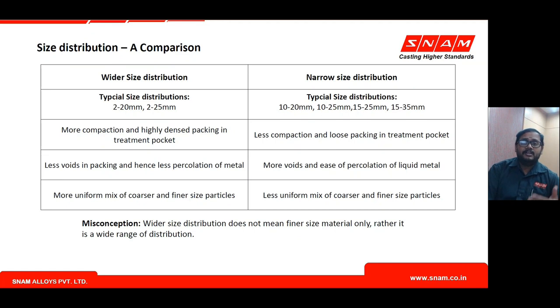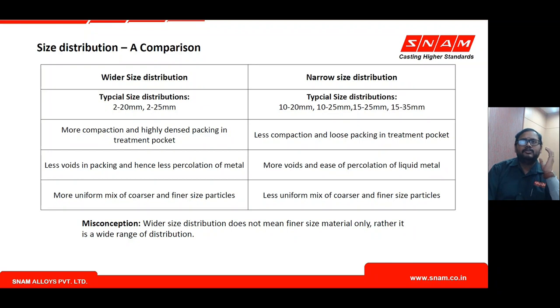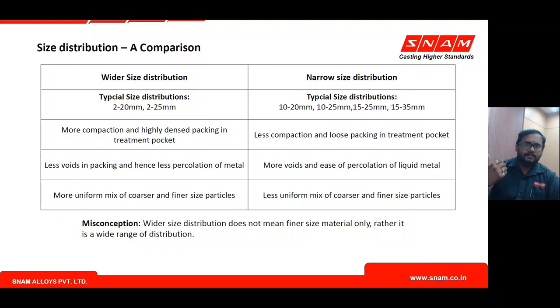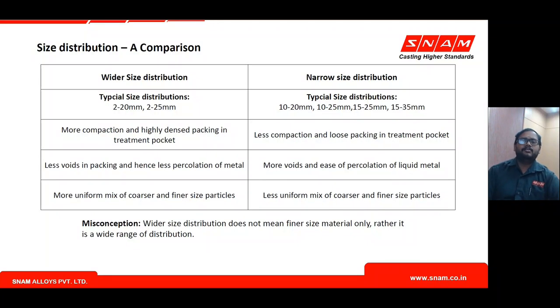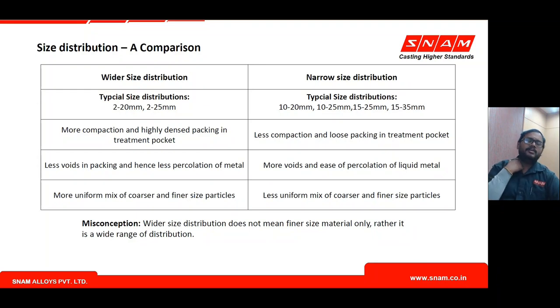With narrow size distribution and loose packing, liquid metal readily passes through the packing, dissolving material early. Because these materials have a lower density than liquid iron, the entering liquid metal with higher velocity can lift the alloy material. This flotation of coarser material occurs when there is less packing. In contrast, compacted wide size distribution prevents this flotation and ensures better retention.